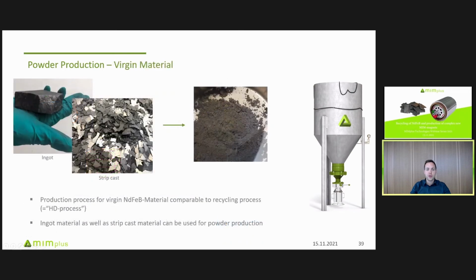If you use virgin material, you have two sources. First could be ingots. It's just molten material cast into blocks, or you can use strip cast material, which is rapidly quenched molten neodymium iron boron alloy. You get it in small flakes, and this can be fed into the HD reactor, the hydrogen decrepitation reactor. Then you get the powder which has to be processed, for example, by milling, as is state of the art for pressed and sintered magnets.